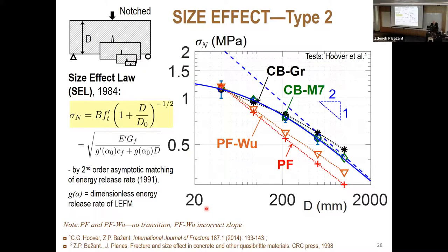Now the comparisons. Most important for fracture, especially of quasibrittle materials, in my opinion, is the size effect. Size effect determines fracture energy, and it also determines the material characteristic length, unambiguously. There was an idea that came up at Northwestern in 1984, and a few years later it was extended to the size effect law: the nominal strength of the structure, a dimensionless parameter, the tensile strength, structure size divided by the transitional size, and that can be related to fracture mechanics by introducing the dimensionless energy release rate as a function of relative crack length. Alpha zero is the initial crack length. Here is the fracture energy, and here is the characteristic length.